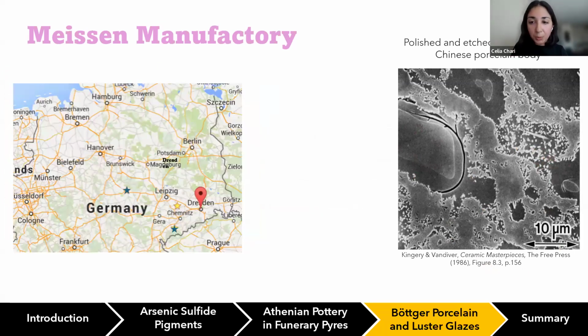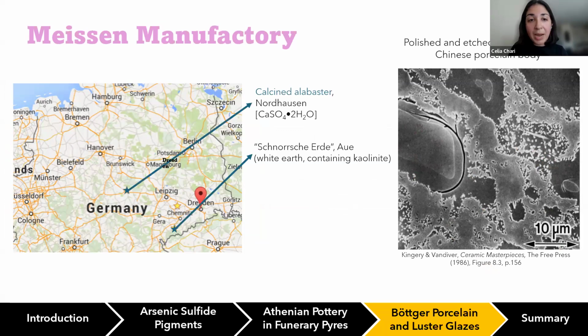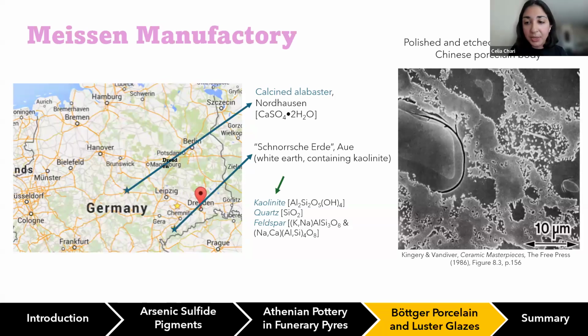In contrast with European porcelain, the earliest bodies, which are referred to as Böttger porcelain, combined powdered alabaster with Schnorr's earth. And Schnorr's earth contains kaolinite, but it also contains quartz as the temper and feldspar as the flux. And this combination of ingredients for the porcelain paste resulted in porcelain bodies that were richer in calcium. So this was smart because it meant that the firing temperature for porcelain decreased significantly compared to what was used in the Far East. So it was easier to produce in a way. And yeah, it's through trial and error that these recipes were refined within Meissen.